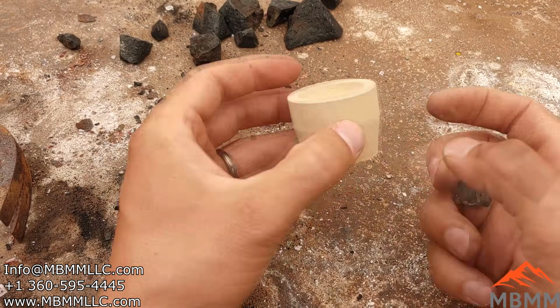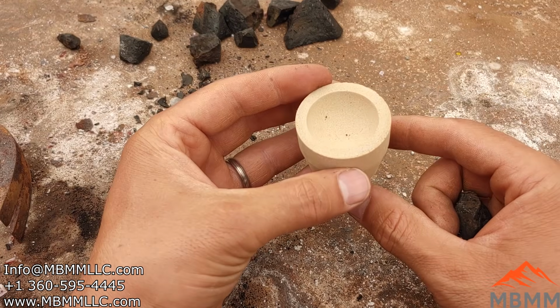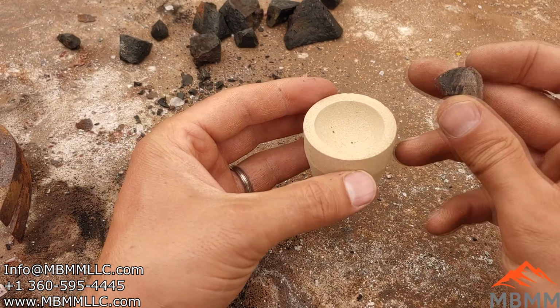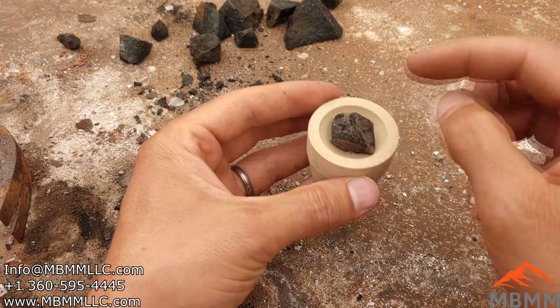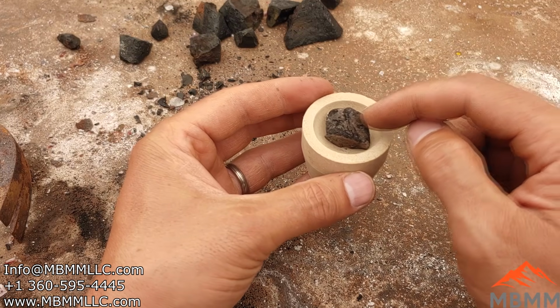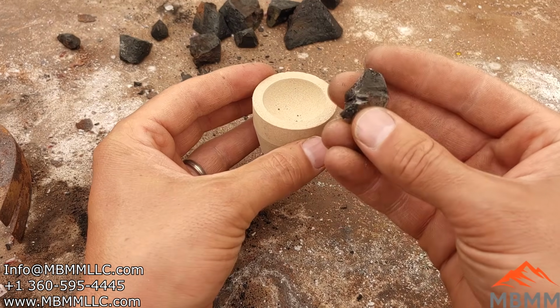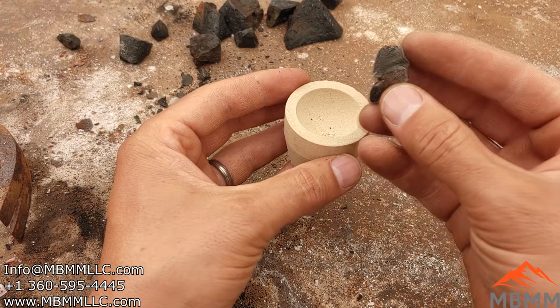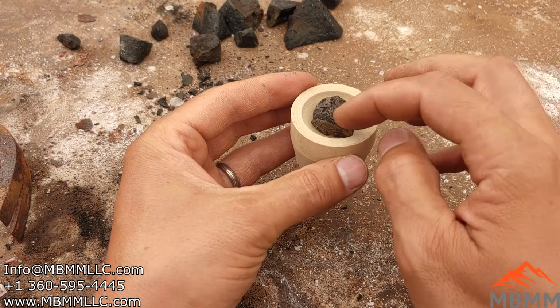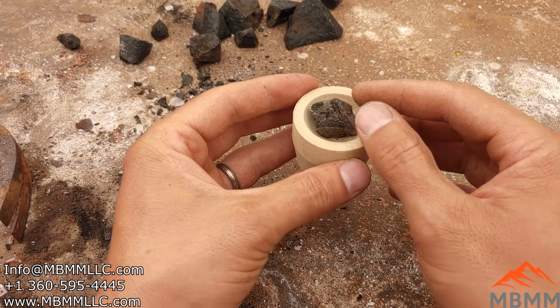All right, well, we got our lead button hammered, knocked as much slag off as I could. Now we're going to put it in this cupel and put it in a furnace at about 1800 degrees Fahrenheit. I weighed the lead, by the way, and it weighs 35 grams. So we started with 50 grams and ended up with 35 grams of lead, hopefully alloy. Hopefully there's some silver in here.